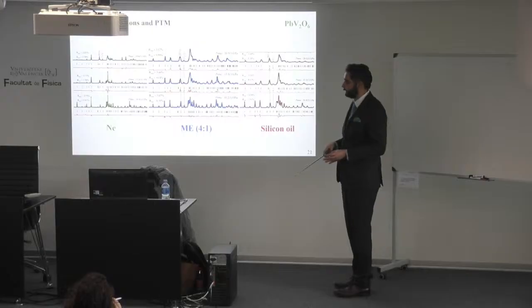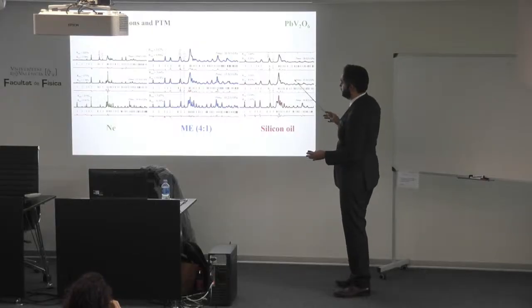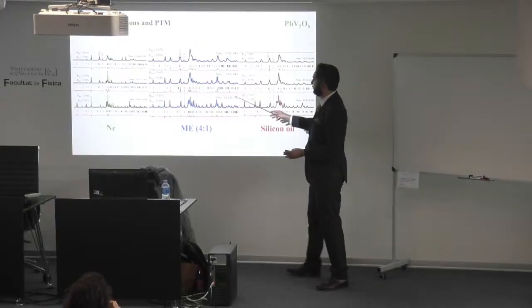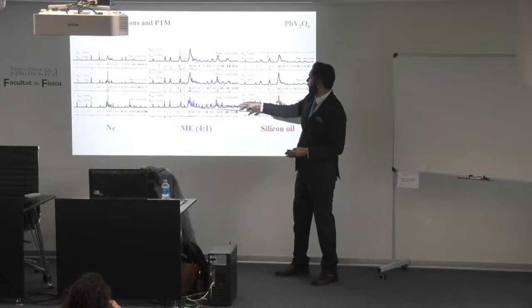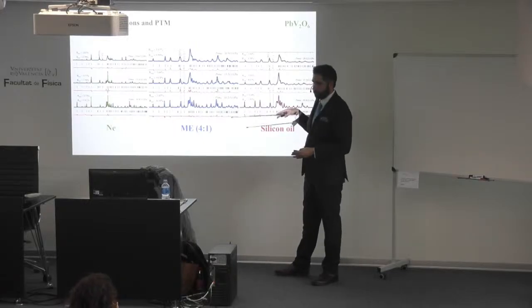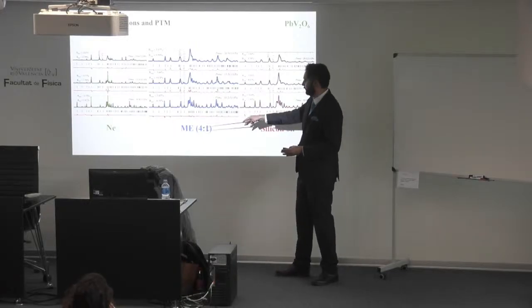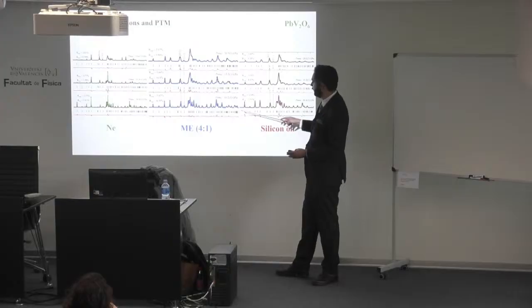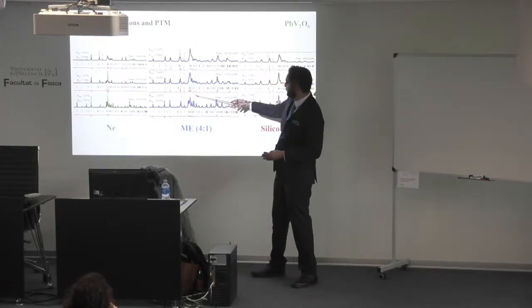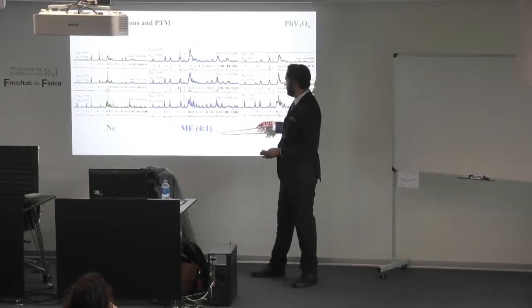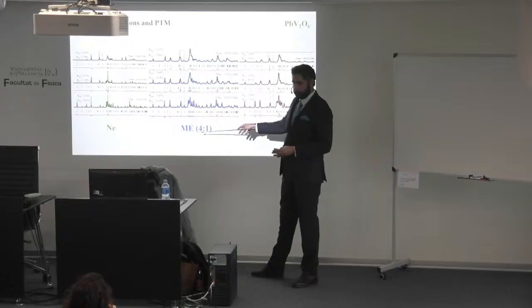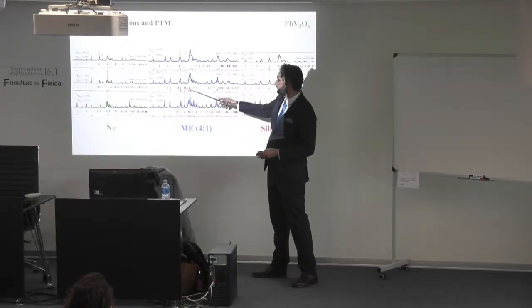Okay, so for lead metavanadate, we had its own structure, different from the typical Brannerite type for the metavanadates. In this case, we saw with pressure, this is for the pressure transmitting media that we used, neon, methanol-ethanol, and silicon oil, these two peaks, when using liquid pressure transmitting media, went to the left.